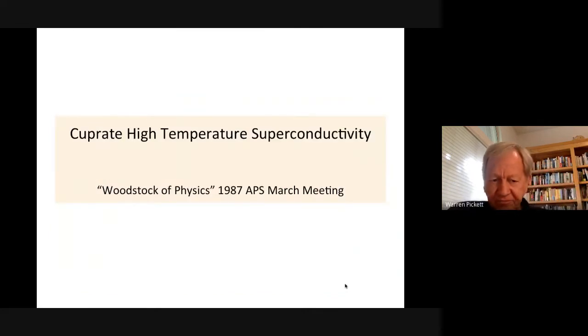Okay, so I'm gonna just mention cuprate high temperature superconductivity. It's different. In 1986, two men, whom I will show the picture of on the next slide, I believe, found that an oxide, copper oxide, became superconducting at about 30 degrees Kelvin, and the rest of the world began working on this. And within 2 months, early 1987, it was found that an yttrium barium copper oxide had a superconducting TC of 90 degrees Kelvin already.